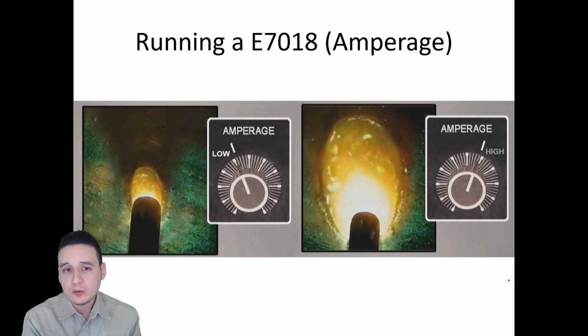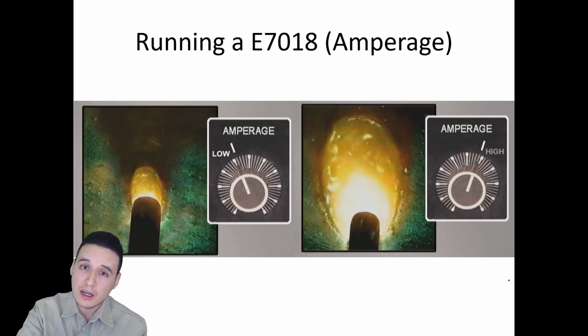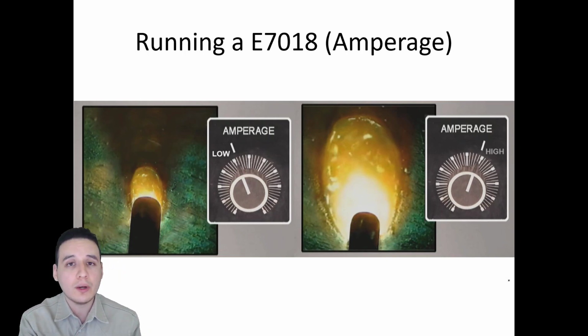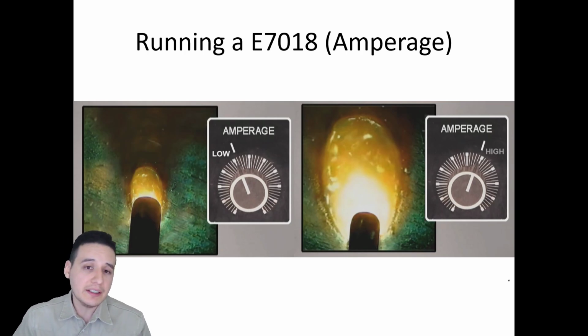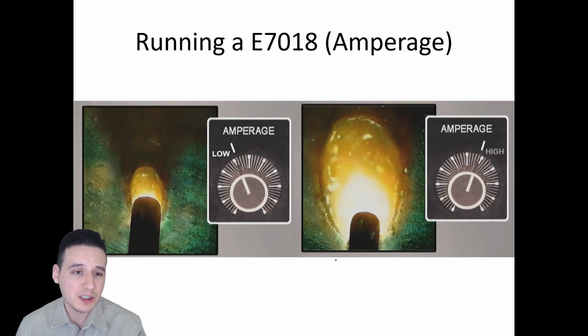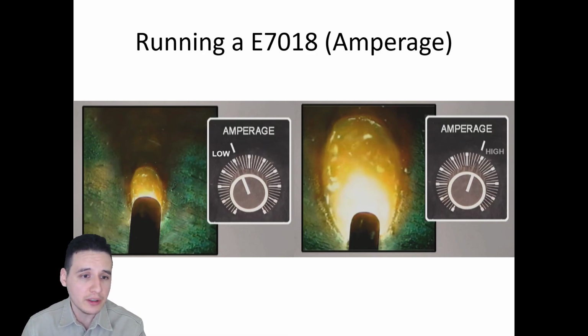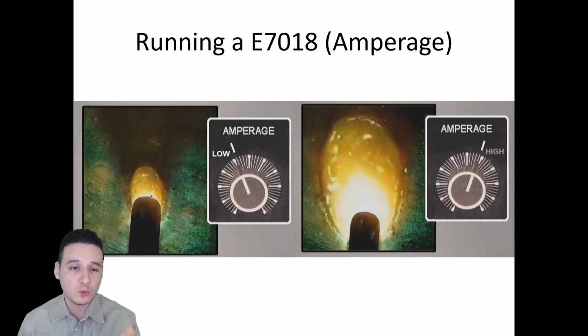How do you know whether you're welding at a low amperage or if you're welding way too hot? And so we know that the easiest way to see that is by simply looking at our weld puddle. In this example here, you could see how big the rod is as opposed to the actual weld puddle that we have there. That weld puddle is way too small. You at least want your weld puddle to be maybe about 3 times bigger than this.